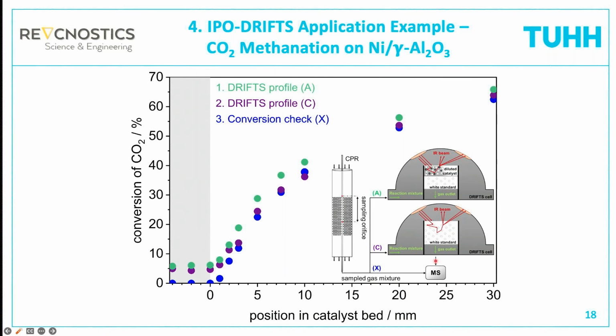And now we can compare this curve to the conversion profile that we get when we go through the drift cell, which is filled with pure calcium fluoride only. And calcium fluoride is very inert. It won't do any chemical reactions. But you see that we already get 5% conversion even before we go into the catalyst bed. So this is the blank reactivity of the drift cell because there is a metallic interior and there is a heating element. And so there are some blank reactions.